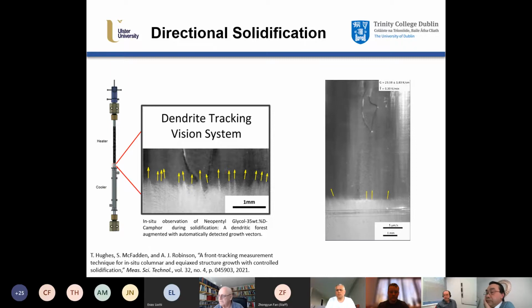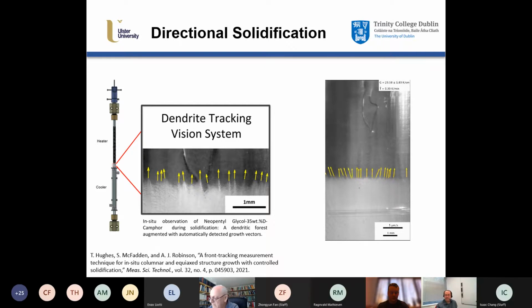So you should see the apparatus here. We do solidification from the bottom up, and behind the dendrite tips, it's quite translucent and very difficult to pick up some detail. But at the dendrite tip itself, you can see some detail there. With a very robust and very novel algorithm, you're able to determine both the velocity growth rate and the orientation of the dendrite tips.